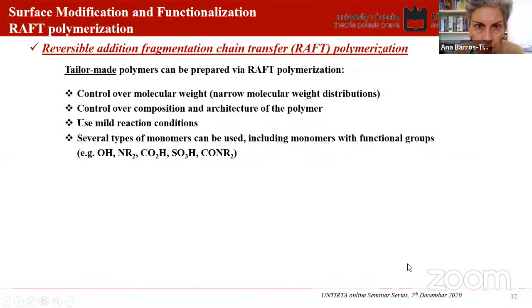But as I said, the idea in this talk is to tell you more about different strategies to functionalize and modify the nanoparticles using RAFT polymerization. So RAFT is a reversible addition fragmentation chain transfer polymerization. The greatest advantage of this polymerization mechanism is that it allows us to prepare tailor-made polymers, and in that sense we can control the molecular weight, so obtain narrow molecular weight distributions. We can control the composition and architecture of the polymer.